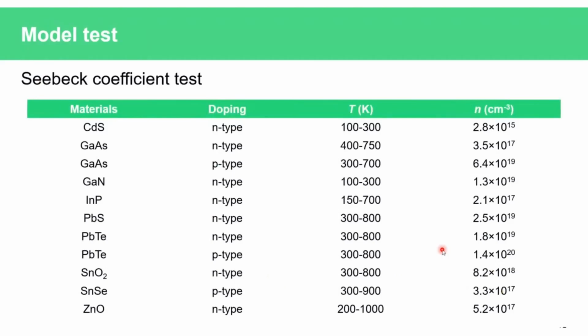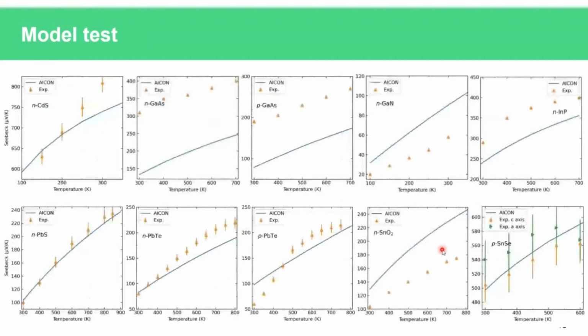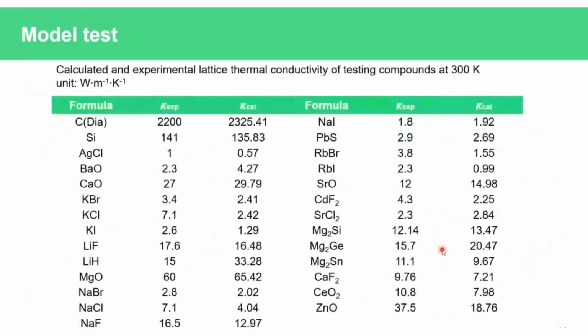This table shows compounds for testing the Seebeck coefficient model, and this page shows the result. Again, reasonable agreement with experimental values is achieved for all these testing samples.